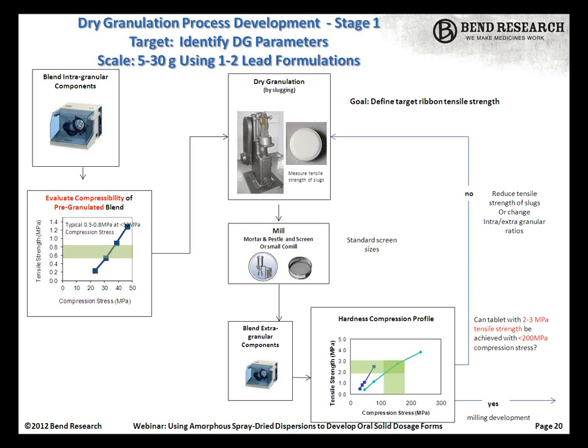If we don't achieve that, then we would go back to alter the composition or the dry granulation solid fraction or the density, so that more compressibility remains in the total formulation. So again, this is all at small scale at 5 to 30 grams.